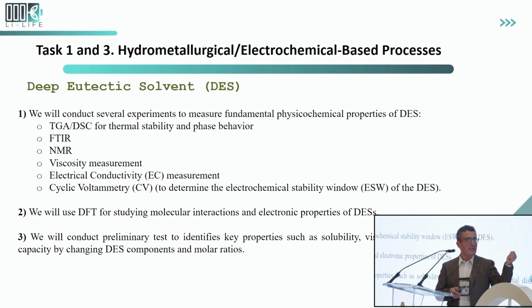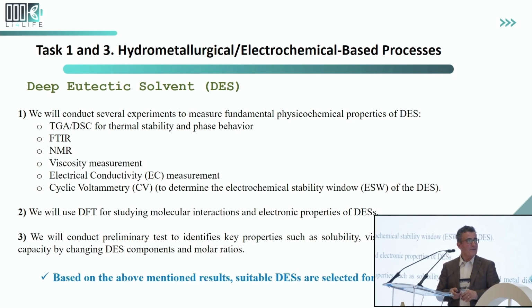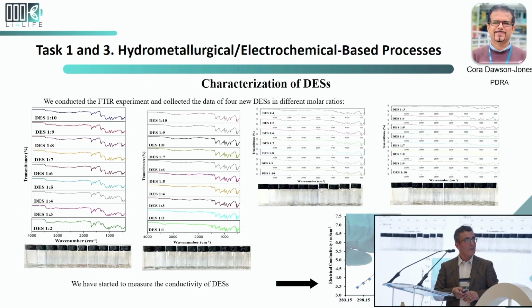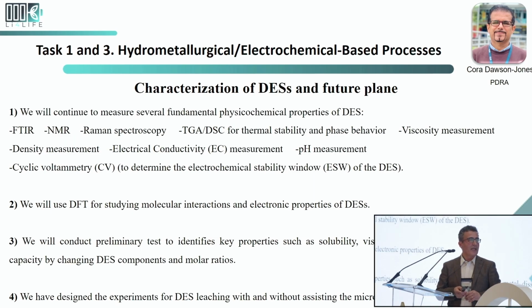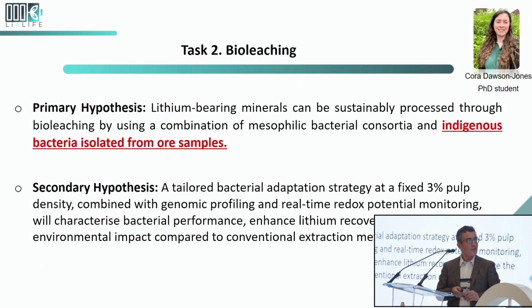These are the list of tests we do for each eutectic solvent in terms of FTIR, NMR, viscosity, electrical conductivity, CV, and also EIS. These are some of our initial results, where we have already narrowed down to three aprotic solvents, which we apply in our leaching processes.